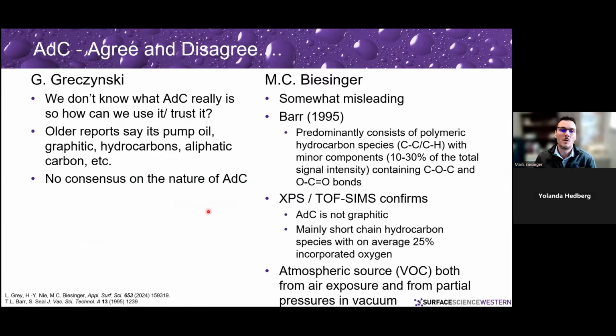He says, we don't know what ADC is, so how can we use it? How can we trust it? Fair point, but somewhat misleading. Barr in 1995 did a study and showed, basically what we found, that it's mostly polymeric hydrocarbon species with minor components, 10 to 30% of the total signal, being oxygen-based as well. So we've done that as well. We've done XPS and ToF-SIMS. Yes, it's not graphitic. It's mainly short-chain hydrocarbon species with about 25% oxygen.